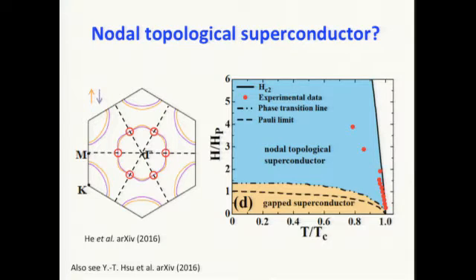Generally, if you have heavier elements, you will have stronger spin-orbit coupling and electron-phonon interaction. Why don't you see that? Okay. So when you go to heavier elements, one thing that would decrease TC from the BCS theory is that the Debye frequency would decrease. Right? So that would decrease the TC.